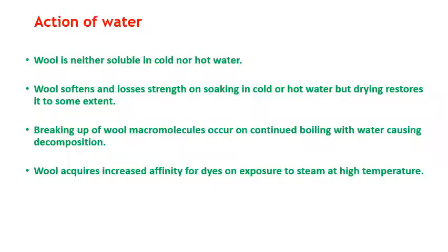Regarding the action of water on wool: wool is neither soluble in cold nor hot water, but softens and loses strength on soaking. Drying restores most properties after cold water exposure, but hot water may cause some permanent effect — that is why woolen garments should not be washed in hot water. Continued boiling with water can cause decomposition of wool macromolecules. Wool also acquires increased affinity for dyes when exposed to steam at high temperature.